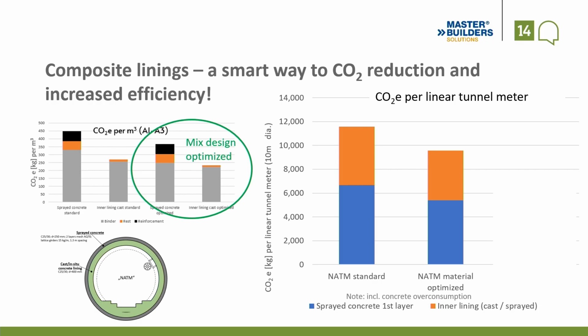Why? I think everybody in the room knows that we use more sprayed concrete than the design asks for. The factor, when I started, was 3. We were in the dry days, now it's about 2. Based on my discussions with my ex-colleagues from site, I have added to the design thickness of sprayed concrete 150 millimeter for excessive thickness, the unforeseeable overbreaks or whatsoever, or to meet the minimum thickness, and 10% for the rebound and the rest with the overconsumption, rest volumes and discharge and whatever, and 10 centimeter for the cast inner lining. So now we do the optimization of the materials. You get it down by 2 tons to below 10.